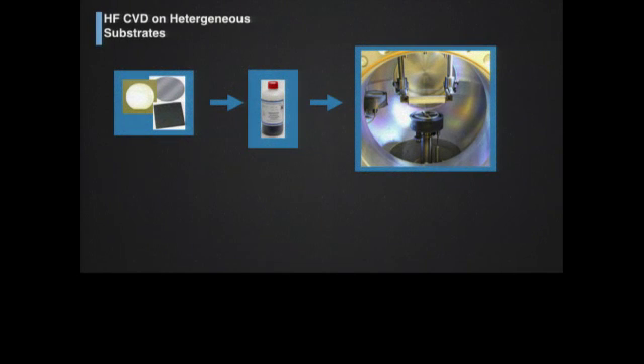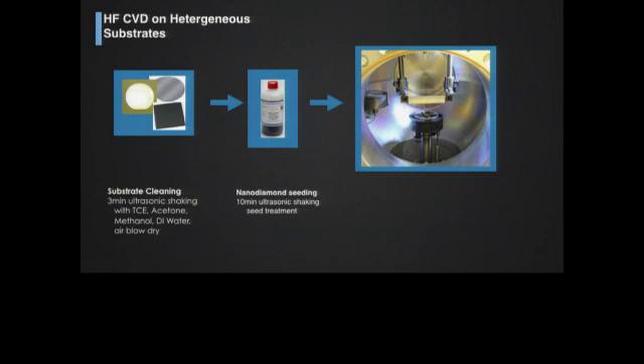So how do we grow heteroepitaxial diamond on top of a foreign substrate? What you have to do is create a lot of nucleation sites for the micro diamond or nano diamond to initiate its growth. One way that we do that, and there are lots of ways to do that, is we use a diamond slurry that we actually spin on to the surface of the material. It leaves behind these nanoparticles of diamond, and then they act as nucleation sites for the growth of diamond, and that coalesces into a continuous film.